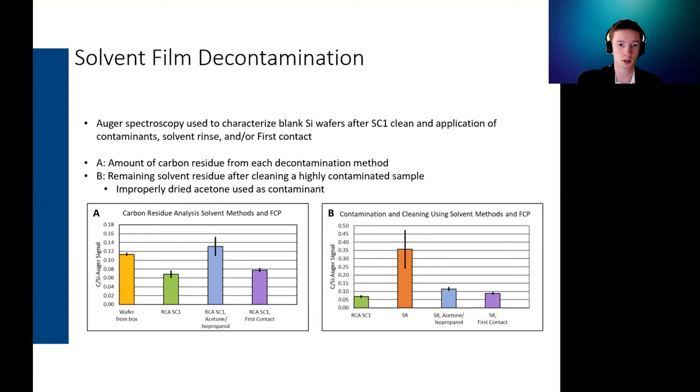The other decontamination area that we looked at was cleaning or removing thin solvent residue films. Using the Auger spectroscopy system at UW-Eau Claire, we tested unpatterned silicon wafers for these first tests. We were able to obtain a quantitative measurement by comparing the carbon signal to the silicon signal from Auger. The plot on the left is describing the residue left behind after each treatment. We have a wafer fresh out of the box, and then we did an SC1 clean, a standard clean one by RCA.